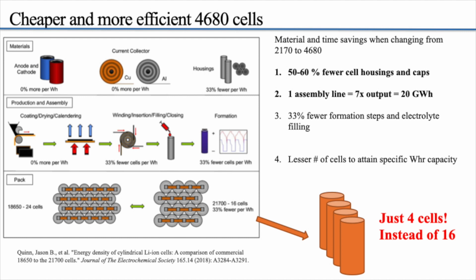The pack would need, they do ultrasonic welding, right? And the amount of times the machine has to stop and go will be reduced. The amount of material needed to weld, the strips needed to weld, would be reduced. And they just need to weld 4 cells instead of 24 in the case of Model S. Imagine the Model S has 24 cells of 18650 for a certain amount of energy. It's just 4 cells if we used 4680 in the Cybertruck or the Semi.